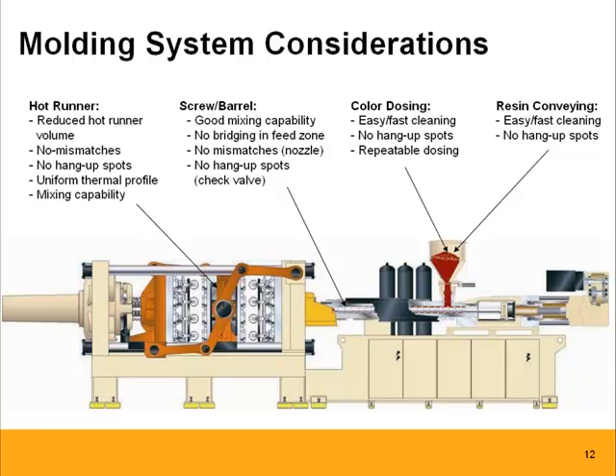In your hot runner itself, what we're looking for, as an overview, is to reduce the volume of the melt channels. The less material we have to replace, the better. We want to have no mismatches. We want to have no hang-up spots. And one thing we'll talk a little bit more about a couple of slides down: a uniform temperature profile is also very important for an optimized color change. And if possible, some mixing capabilities in the hot runner itself for further color distribution.